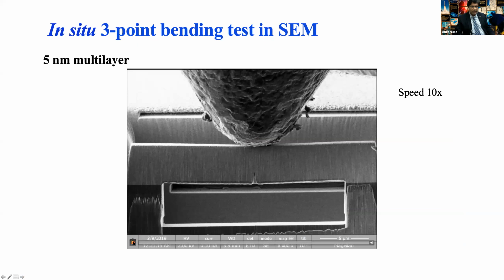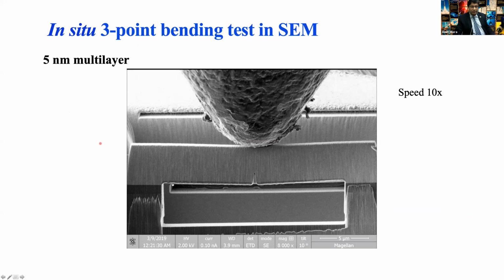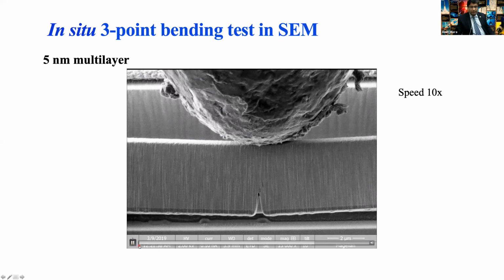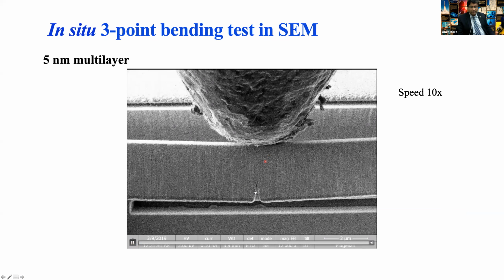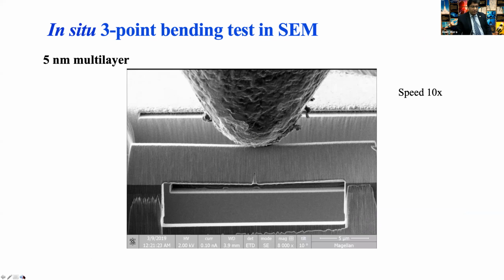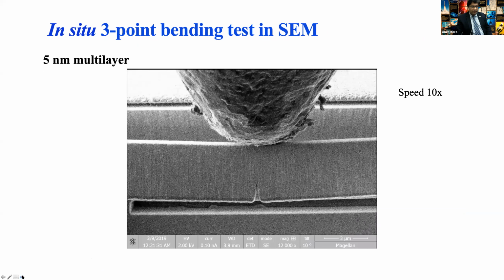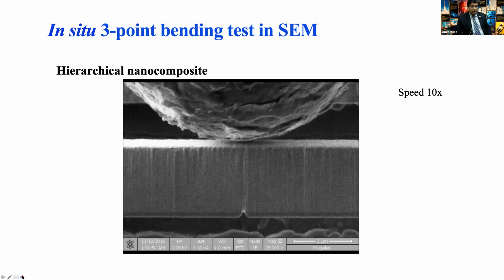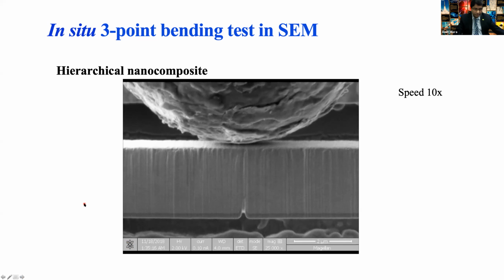So this is a bend test in situ for a multi-layer, and you'll see that as soon as the crack formed at the notch, just in one frame, the sample just fractured. There was no crack growth resistance. As soon as the crack popped, it just failed in one frame. How is this different when you have the, go to the next slide here. Yeah, so this is the hierarchical structure. You will see a very different response here.